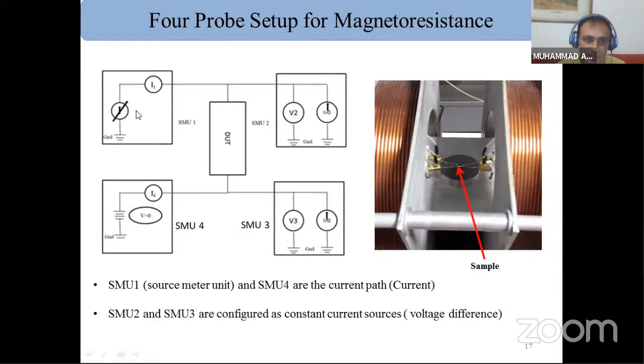SMU1 I have used as a variable current source. SMU4 is also a variable current source, and these two, SMU2 and SMU3, are used as voltmeters. I make sure that the current flow through SMU2 and SMU3 is zero, so that they behave like a voltmeter, so that I can measure the voltage difference of the device under test. Here I can measure the current, here I can measure the voltage, and by measuring current and voltage, we can easily get the magnetoresistance of this device under test.